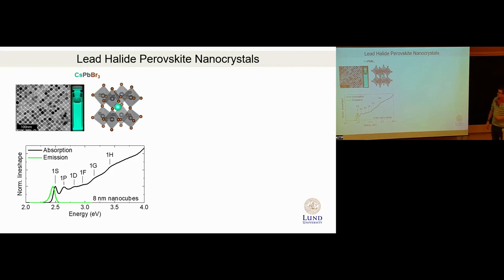Typically, I'll be talking about cesium lead bromide, which is prepared in the form of nanocubes. Here's an example of the structure of this perovskite. You have lead bromide octahedra interconnected in three-dimensional networks with the vacancies in between filled by a cesium atom in this case. It can be methylammonium or another monovalent cation. When you make them of sufficiently high quality, you see this nice absorption spectra, which you can describe, for example, by assigning it particle-in-a-sphere-like electronic states.